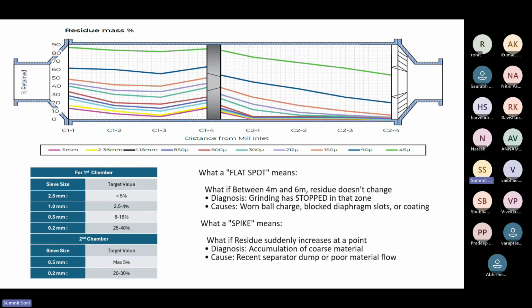Similarly, for the second chamber at the diaphragm, you should check the 0.5 mm. But when it comes to second chamber, I usually trust the Blaine, the difference of Blaine at the end of the mill and at the first sample. That's a better guiding value. It's more global because then we are actually taking the whole mill into consideration.